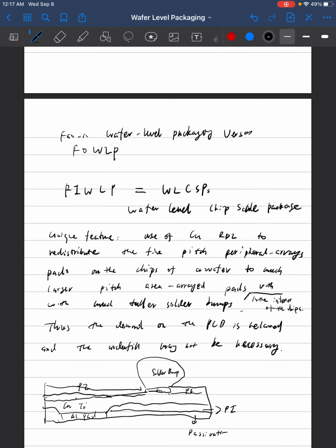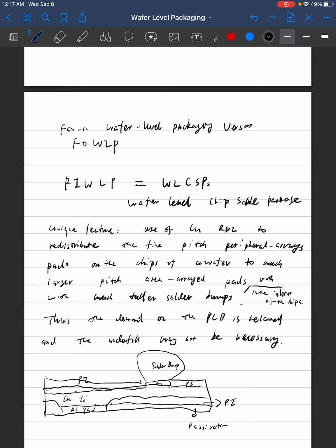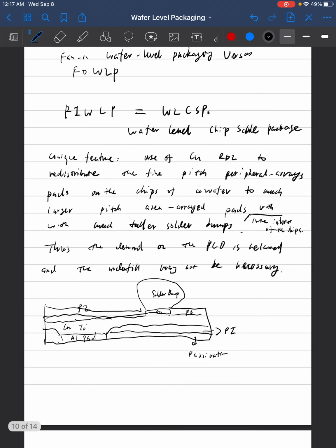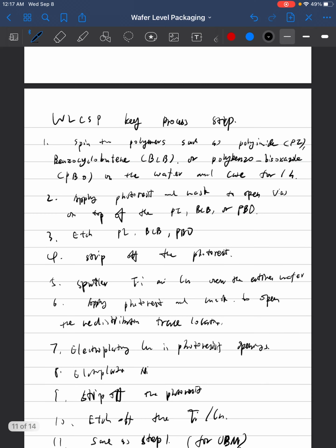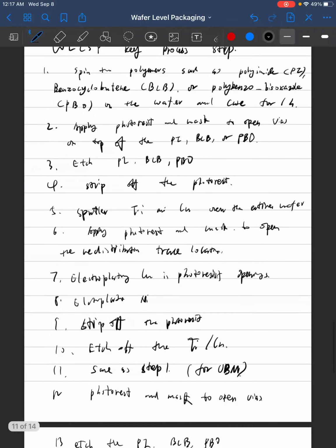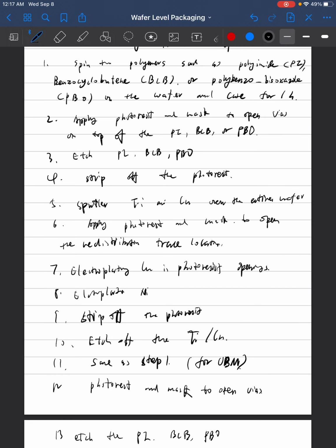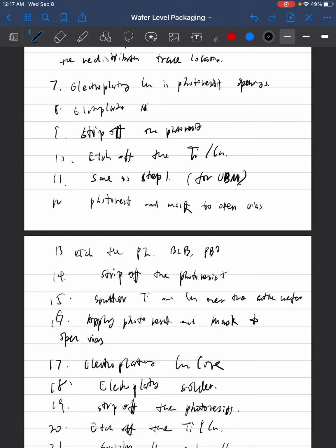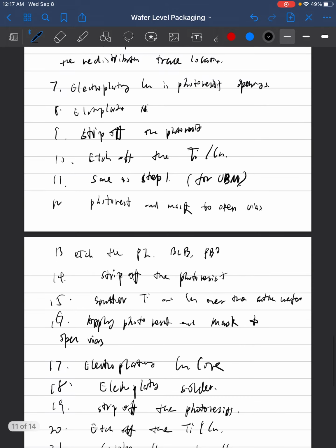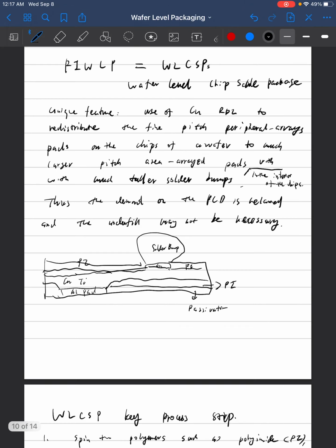By doing the packaging in this way, the demand on the PCB is released and the underfill might not be necessary. This figure shows typical structures of the fan-in wafer-level packaging, and the key steps are written below. So basically, we follow the spin coating of the photoresist, open the photoresist with mask and UV light, doing the photolithography to open the vias and etch away, strip away the photoresist, sputtering, coating and depositing metal layers, and then repeat different processes to fabricate the redistribution layers so that, like we said, we can transfer the fine pitch on the peripheral array into the interior area array pads.